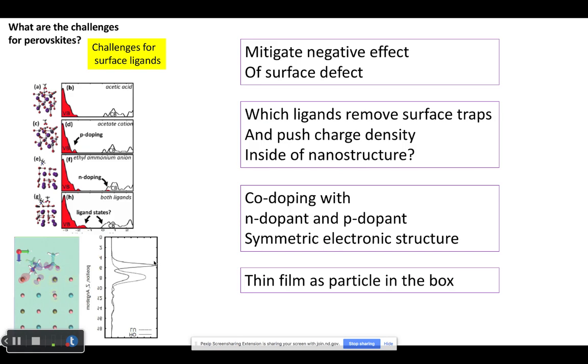Another research that we hope will be updated today by Daniel Ramirez deals with flat surfaces for photovoltaics applications, where a rough surface without ligands or with wrong ligands may have affinity for surface defects, surface traps, and be not applicable for applications. So there is ongoing research of finding pairs of anion and cation ligands that would match the crystallographic symmetry of the original perovskite, hold there tightly due to electrostatics, and push charge carriers, electrons and holes, inside the perovskite.